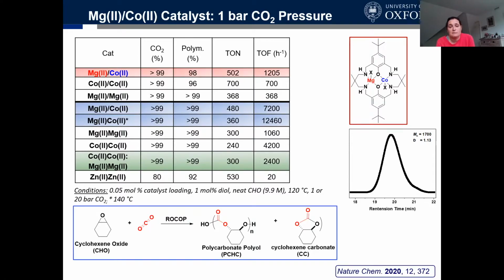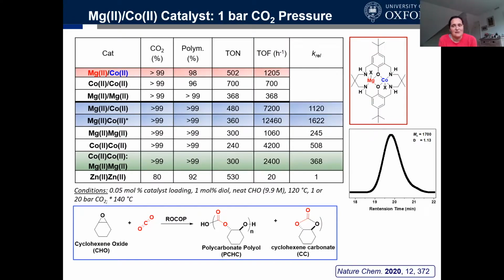It also outperforms mixtures of the two, which just give the law of averages, the rule of mixtures value. And that's because although over time, cobalt and magnesium would redistribute to give the heterodinuclear compound, they don't do so on the timescale of these experiments. And way back at the bottom is what happens with zinc, and you can see where we began and how far we've come, as it were, over a quite significant period of time as well, but research takes time.